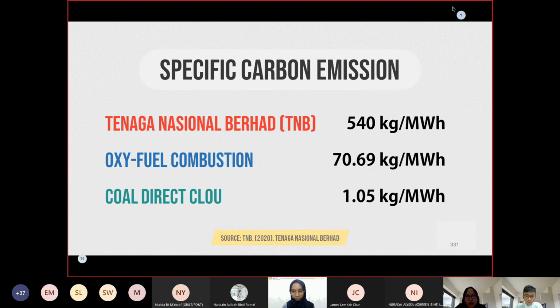However, this is nothing when compared to coal direct CLOU. With CLOU, we can go as low as 1.05 kg per megawatt hour, which is a few hundred times lower when compared to TNB. Although this does not reflect the real scenario, as this is just a simulation, this shows the potential and sets the upper bound of what CLOU is capable of doing.